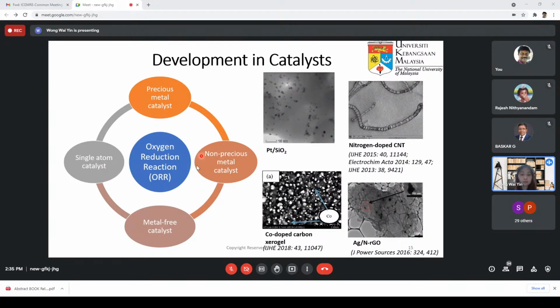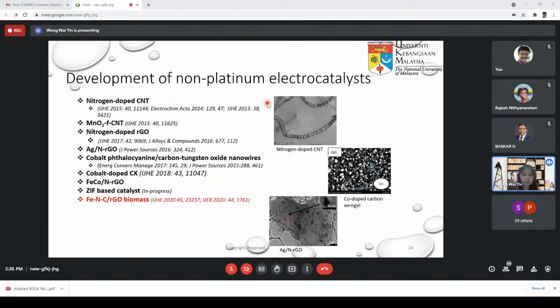And when we talk about the non-precious metal catalyst, we find that until today, where the active sites for this catalyst are is still ambiguous. We're still speculating. So there are also attempts at studying single atom catalysts to examine the actual active sites of the catalyst itself. Okay, so these are a few main areas that we are looking into for oxygen reduction reaction catalysts. And on the right side, these are the works that we have done in our lab. This is the list of the development of non-platinum electrocatalysts in our laboratory.